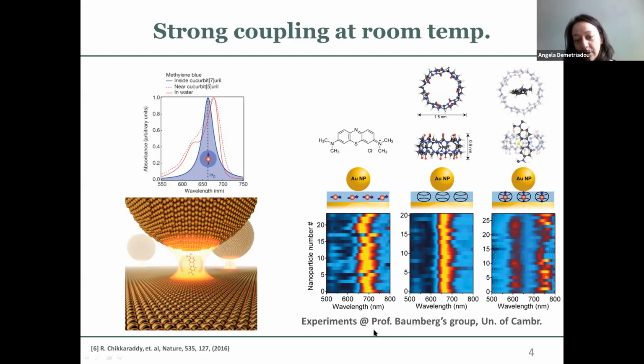And here are the experimental results from Jeremy Baumberg's group, where if you sample the same system with the methylene blue parallel, so basically it's not aligned with the field enhancement in the gap, you only see the plasmon, so these are scattering cross sections. If you don't have the methylene blue within this system, you again see only the plasmon emitting to the far field. But once you have the combined system where the methylene blue is inside this host molecule, which allows it to stand up and be aligned with the field enhancement in the gap, you start seeing the two hybrid modes. Basically, your plasmon mode, the one peak, splits and becomes two, which is a clear indication of the strong coupling between light and matter, in this case, the plasmon and the methylene blue molecule.